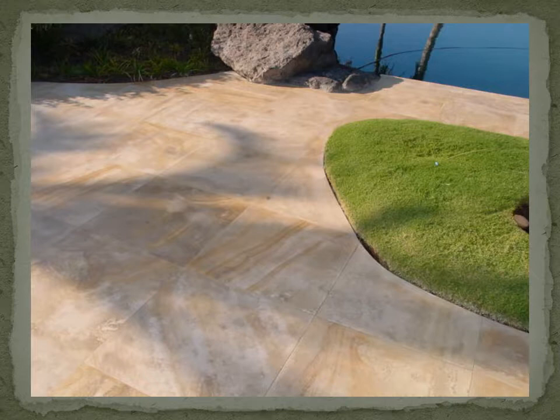This is the same problem on a limestone floor, kind of over in the shadows. You can see it a little bit more. Just an overall darkening. This is where, as you can see, this little landscaped island where the landscaping is raised quite a bit from the adjacent hard floor surface. And it has to get irrigated quite a bit to stay nice and green like that. So all that moisture goes down, and it wicks into the side of the concrete slab and into the mortar bed and into the stone, and leaves all of its minerals behind. The irrigation water that has a whole bunch of silica in it, it's just leaving deposits inside the stone.